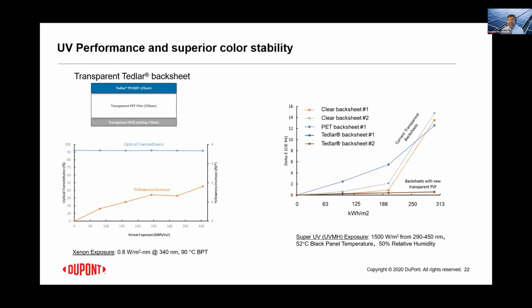Comparing with some existing prototypes of other backsheets in the market, we see that the Tedlar-based backsheet, which is down here, maintains a very low color change, well over 300 kilowatt hours per meter square, whereas some of these other competitors actually are having a significant increase in color, indicating that the polymeric material, which is the main component over here, is changing in some way in the composition. This, by the way, is a metal halide exposure versus the xenon exposure, which was shown on the left over here. It's a much more intense exposure in this case, as you can see from these numbers.